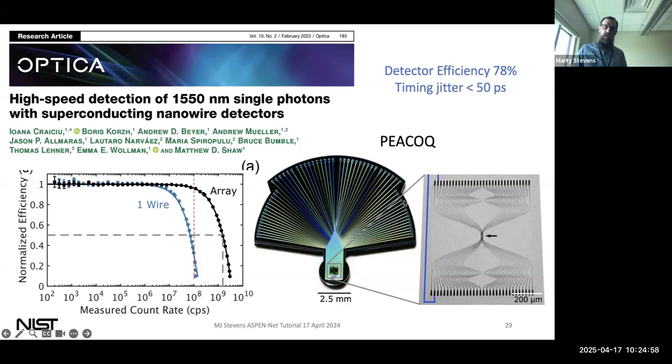Yeah, it's basically because what we need is to destroy superconductivity across that entire cross-sectional area of the wire. And so, as I said, the way we tend to do it, the way the growth and fabrication of the devices works best, we can deposit a thin layer, a few nanometers thick, and then pattern it into, say, 100 nanometers wide or even a micron wide.